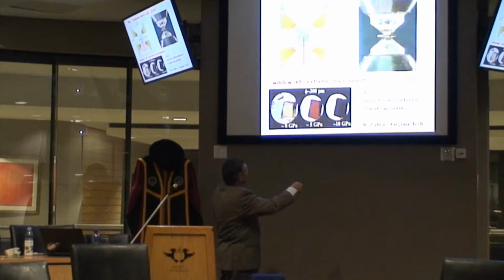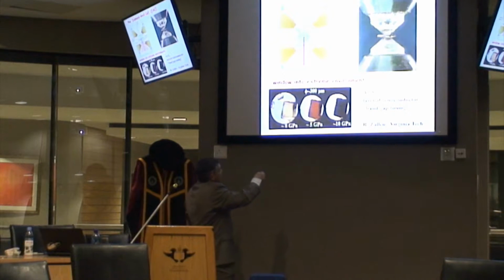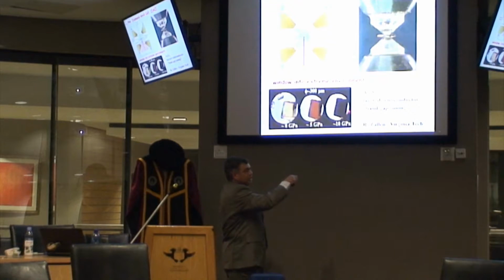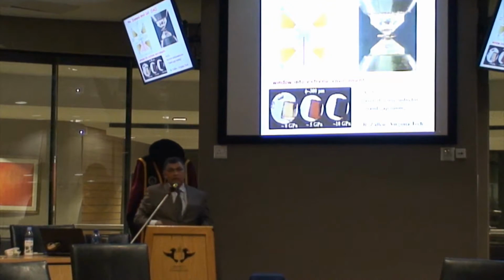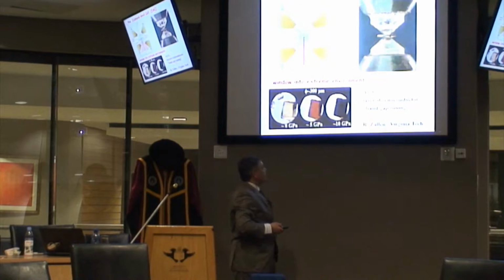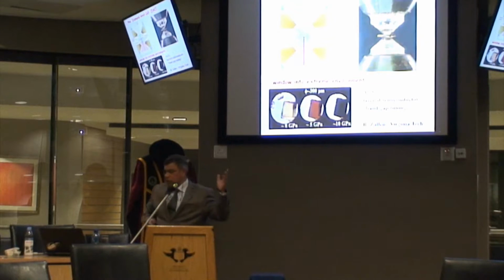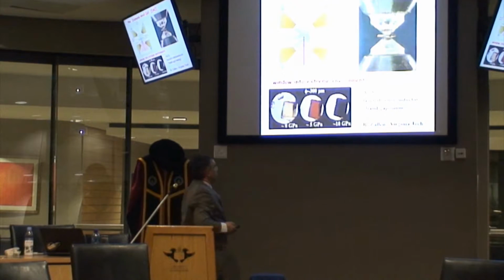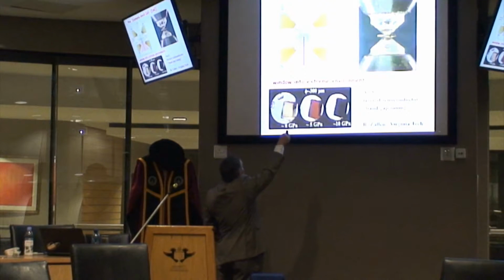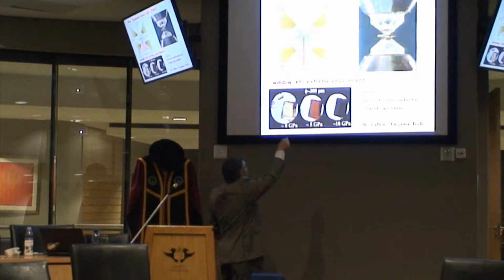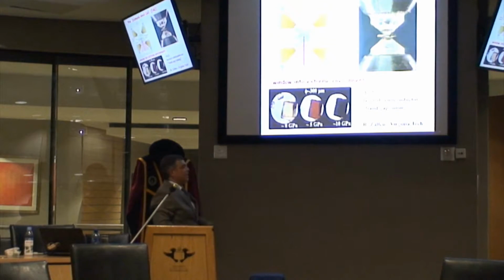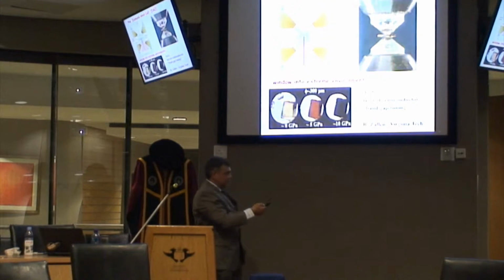And here's a very nice example of how this is a window. This important layered semiconductor near ambient condition starts off yellow in color. This is a view into the cavity through one of these diamonds. Then it changes to a color of red at 50,000 atmospheres. And at 100,000 atmospheres, it's gone opaque. And for the benefit of my physics colleagues, we know what we are doing here. We're tuning the electronic band gap of this material. The important thing is you can also bring different forms of interrogating electromagnetic radiation into this cavity to probe the material, besides viewing it visibly, as indicated over here.